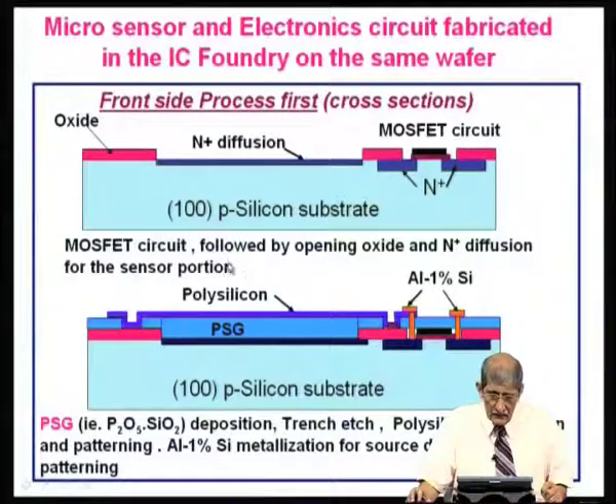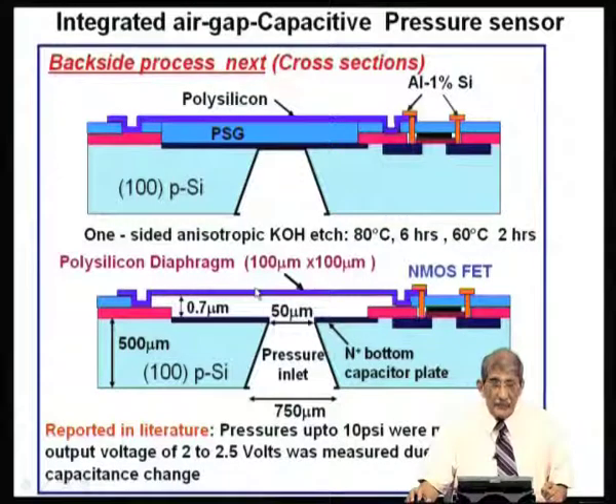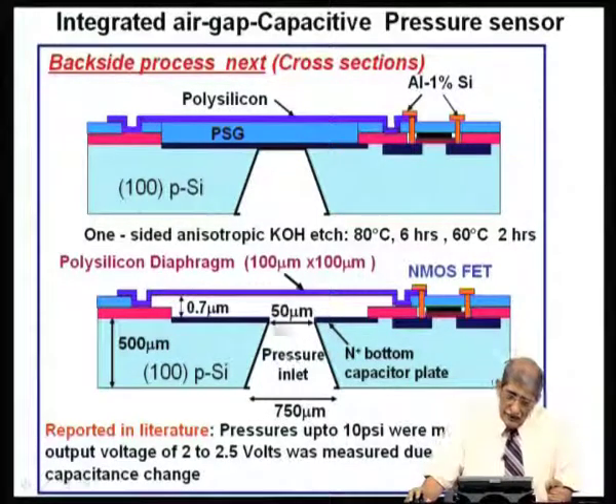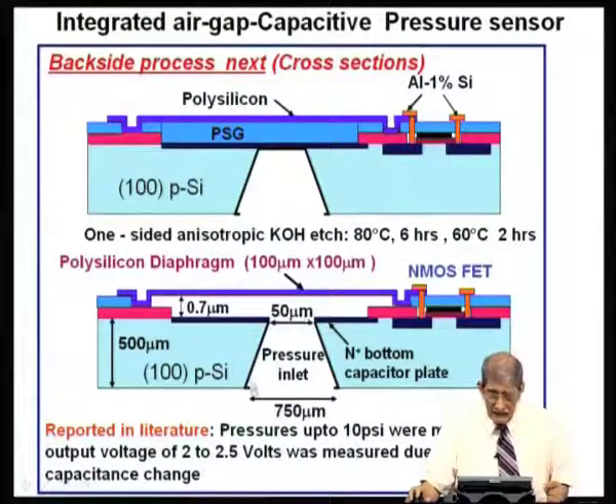This N plus region and this polysilicon are separated by means of the air gap. In this example, it is about 0.7 micrometers. And this hole is about 50 microns only and this is about 750 microns. The size you get here depends upon how much window you opened. For a 500 micrometer thick silicon wafer, if I use about 750 microns, then you will get about 50 microns. So, the size of this hole is decided by how much area you want to open.